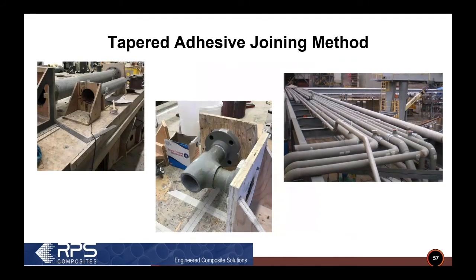And here are some examples of adhesive joints. You can see the guy's making a flange by flange straight piece of pipe over on the left hand side. Here we're making a flange T for a spool in the middle of the picture. And then over on the right hand side, you can see some long pipe racks, and that's a great spot to use adhesive joints because it's simply slipping the 2 pieces together and holding them in place while you do the joint. That taper that's cut on the tapering machine can actually be pre-done in the factory and sent out pre-tapered. So that's also quite common for rack piping.